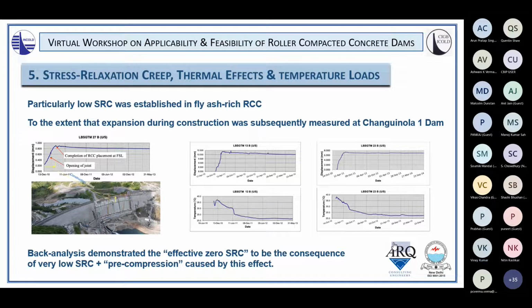So for the continuous horizontal construction above for the non-overspill crest, etc., there was none of this expansion. It only occurred as concrete was placed fully from abutment to abutment horizontally. It happened linearly and stopped. And to the extent on those gauges of indicating an expansion on the upstream side of the order of 72 microstrain.